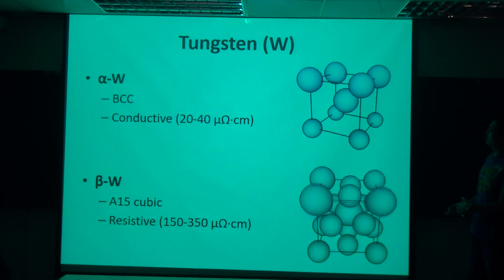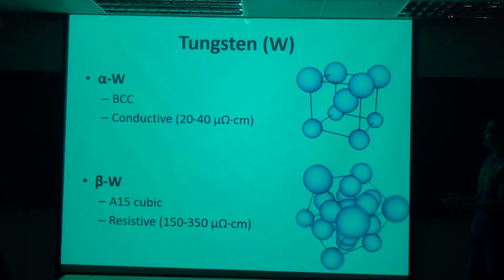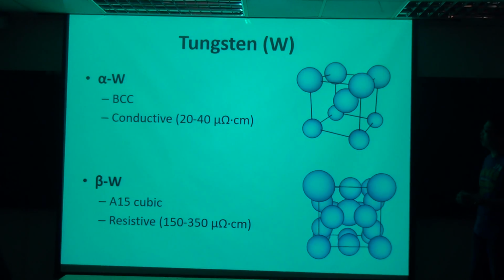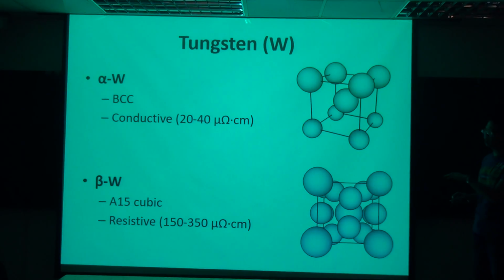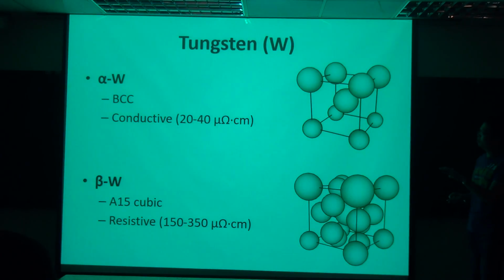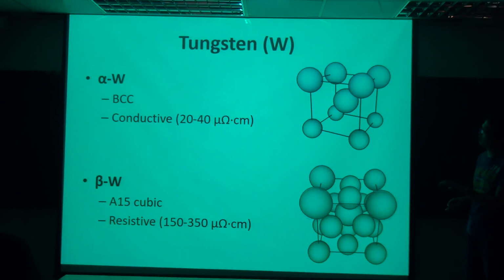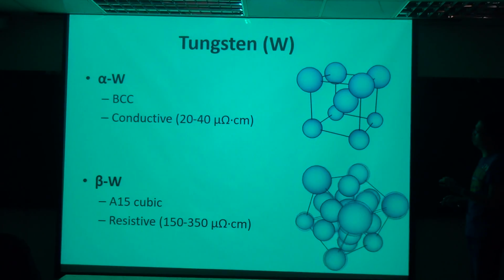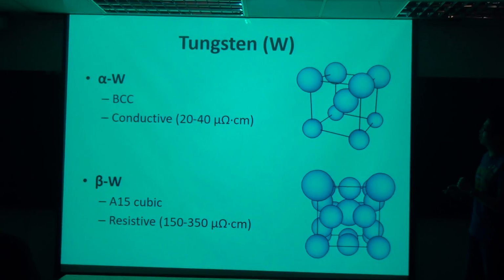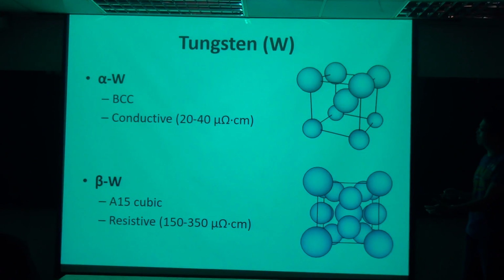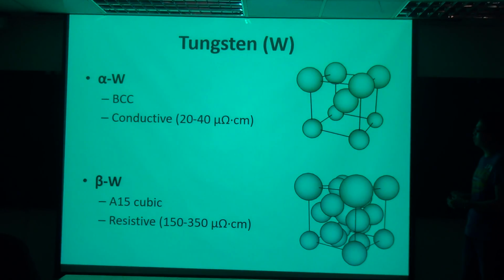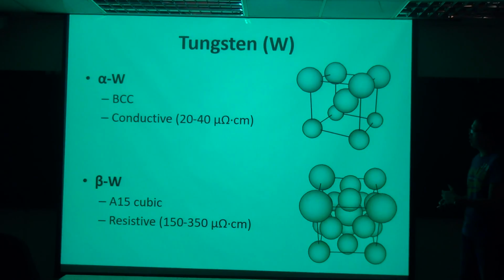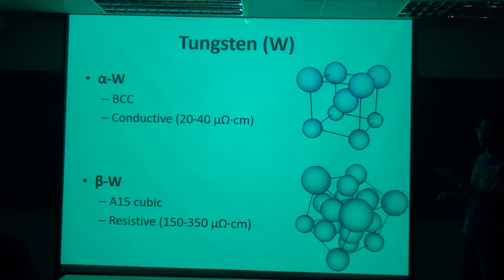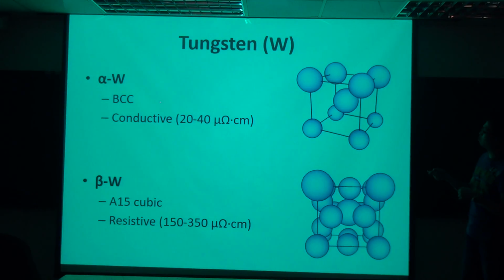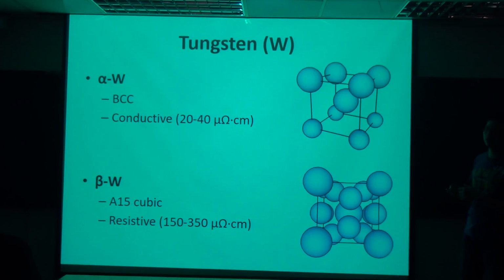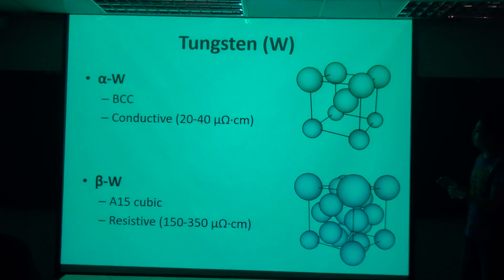And for tungsten, actually there are two phases, and it's even more complicated than tantalum. Because for tantalum, once you sputter it, typically you will just get the high resistivity state, either amorphous or we call it beta tantalum, whatever, but it's always high resistivity. But for tungsten, it's very interesting. If you sputter, say, more than 5 or 6 nanometers, or if you cook it above, say, 150 degrees Celsius, that's right about the typical hot plate temperature, you will get a phase transition from beta tungsten to alpha tungsten. So basically, you have two phases that you can play with.